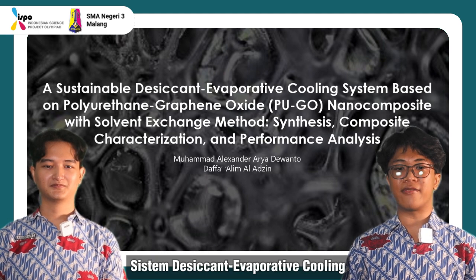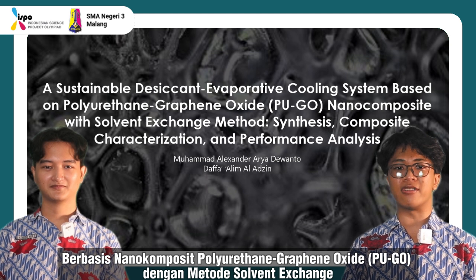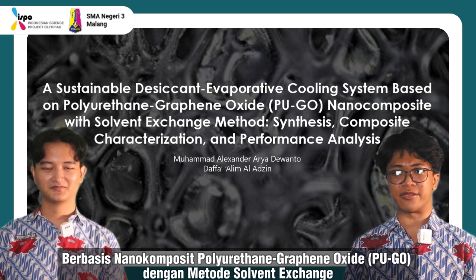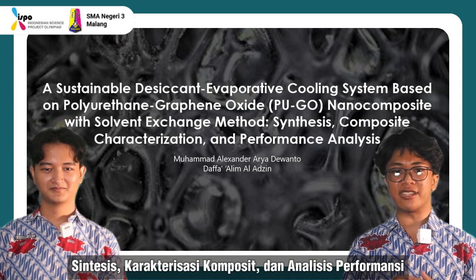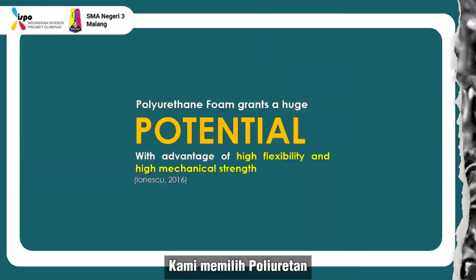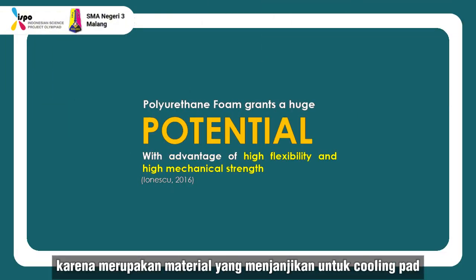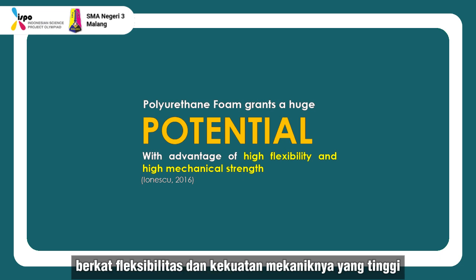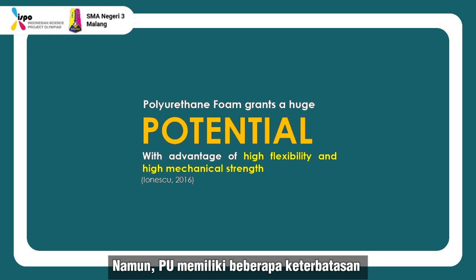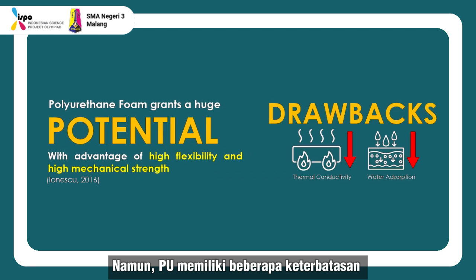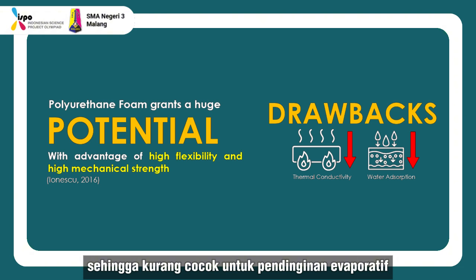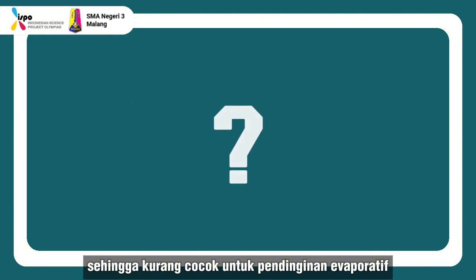A sustainable desiccant evaporative cooling system based on polyurethane graphene oxide nanocomposite with solvent exchange method: synthesis, composite characterization, and performance analysis. We choose polyurethane because it is a promising material for cooling pads, due to its high flexibility and mechanical strength. However, polyurethane has several limitations: low thermal conductivity, limited water absorption, and thermal instability at high temperature, which make polyurethane not suitable for evaporative cooler use.